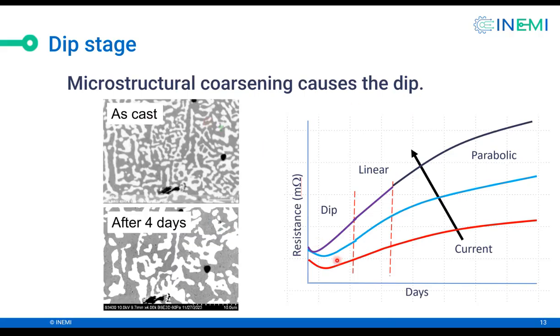The reason we have the dip is because initially the structure is very fine. The white region is bismuth, the gray region is tin-rich. So imagine electrons flowing through this region. They want to go along the dark region because that's tin, which is more conductive, but they meet many obstacles. So they meander through to get from the cathode to the anode, whereas after a few days, the structure becomes very coarse. And now it's easier for the electrons to go through the gray region, so the resistance decreases. That's the reason for this small decrease in resistance.